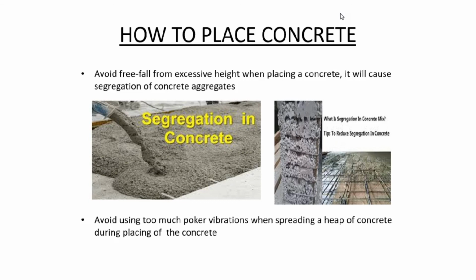On a question paper, you can expect what results you can get when you are placing your concrete incorrectly. You must be able to give the two reasons that we've discussed. Your concrete will segregate, which means it will segregate your material, that is your aggregate. And then you must also not use too much poker vibration, because the poker vibrator sometimes pushes your reinforcement or your spaces, because when you are pouring the concrete surface bed or the slab, there are some spaces, and you must not use too much poker vibrator, especially when there's a heap of concrete during placing of concrete.